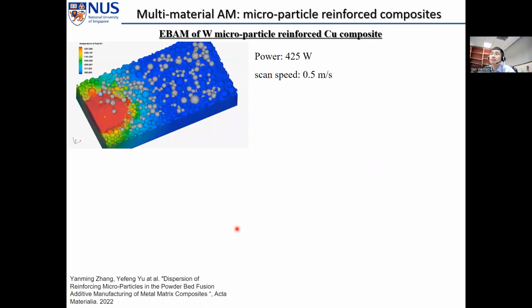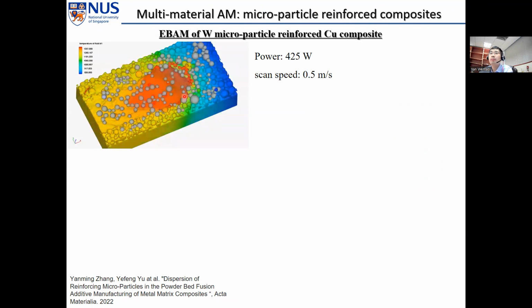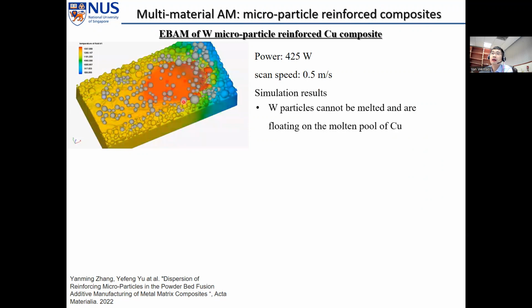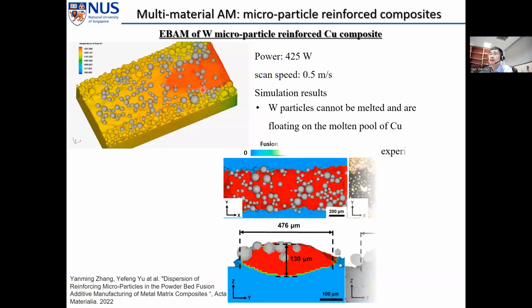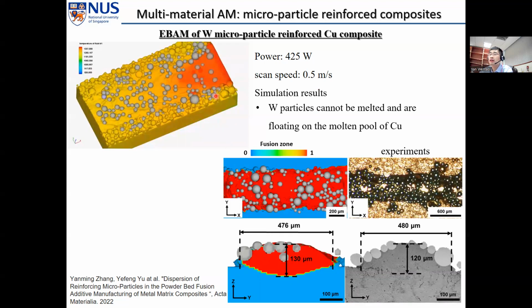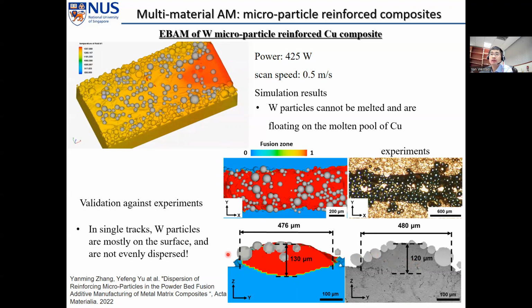Another scenario is particle reinforced composites. This is one example of microparticle tungsten reinforced copper composites. The gray particles are the tungsten particles. They cannot be melted, whereas the copper matrix can be melted, and the copper powder can be melted. You can see all these tungsten particles are floating on the molten pool surface, and just a few tungsten particles can submerge into the molten pool. This is experimental validation. In single tracks, these tungsten particles are mostly on the surface, and they are not uniformly dispersed.